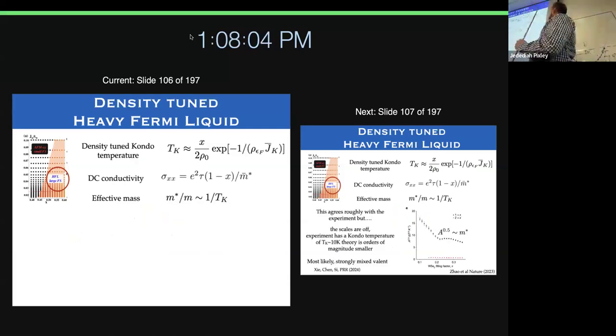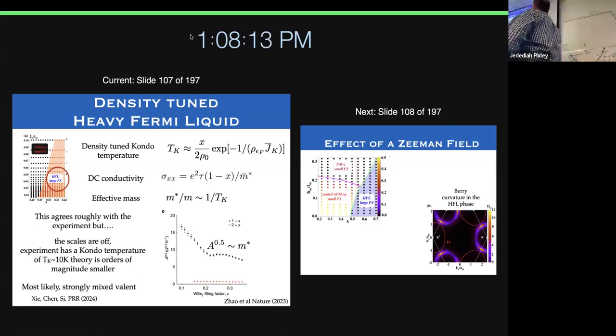So this density tuned Kondo temperature is tied to the density relation to the Kondo coupling averaged over the Fermi surface. And one thing that we're not getting so good is the size of the Kondo temperature. So these are our conclusions, and it roughly agrees with this, but the scale is a bit off. The experiment has a Kondo temperature on the order of 10 Kelvin, we get like 2 orders of magnitude below that. But there's been work showing that it's probably a strongly mixed valent limit that we have not considered here. So that's an interesting question for future work, if we figure out the scales properly.